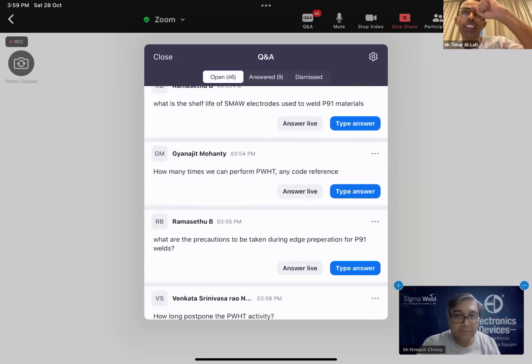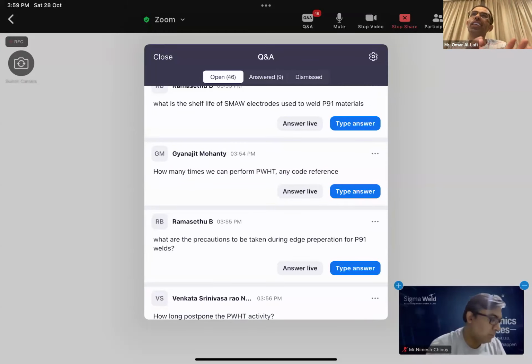I just remembered one case that happened to me. There was a coil of P91 material we cut to do the repair, and we cut the main headers, the outlet and inlet headers, and sent them for repair outside, and there was a hydro test required after the repair. So we had to install blinds, and they brought carbon steel blinds. The vendor did not have a WPS for joining carbon steel to P91 material. So they thought it's okay. This is only a matter of hydro test. We can weld this header to a carbon steel and do the hydro test and then cut it again. So we should be careful in situations like this.